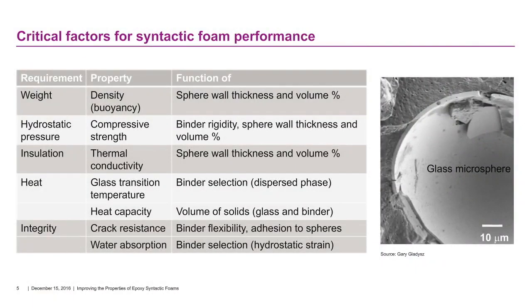The critical factors for the proper performance of the syntactic foams come down to a number of different requirements, and you see some recurring themes here. Before I get into that, just want to direct you to the nice micrograph here on the right, which gives you a really good view of the glass microsphere and the dispersed organic phase, the matrix, and it can be quite fragile, that interface, and the simple formulation has a lot to do with that, as you see here.